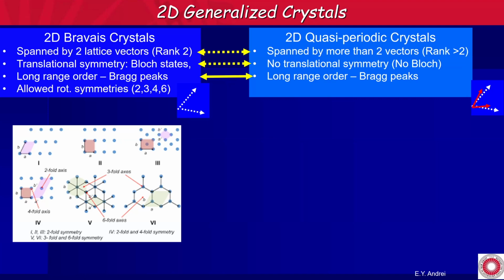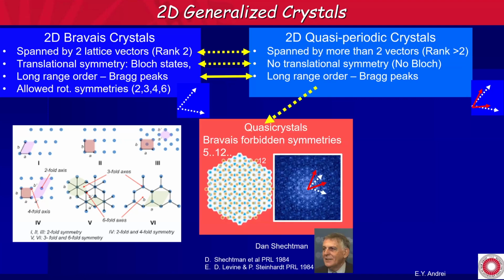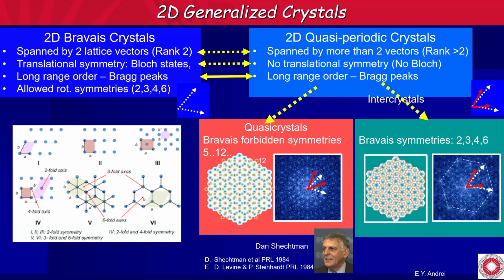So in this category, quasi-periodic crystals, there's 2 kinds. One is a quasi-crystal, which we all know and love, and that has all these properties here, and it must have Bravais-forbidden symmetries, 5, 12, whatever. And the other category, they have all the properties that I listed above, but they do not have a Bravais-forbidden symmetry. It has the same symmetries as before. That's why we call them intercrystal, between crystal and quasi-crystal.